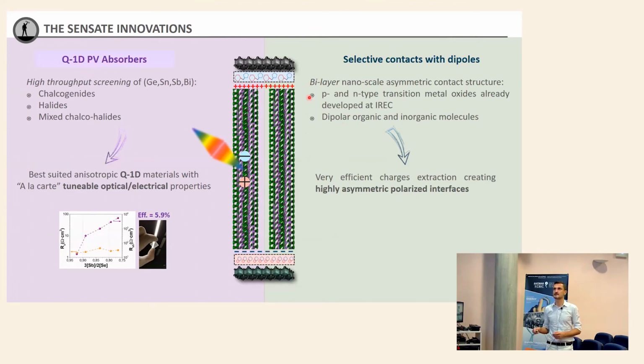absorbers. The characteristic of this material is that they have a very strong covalent bonding in one direction, in 2 directions, sorry, and then you form ribbons. And then these ribbons are bonded among them with van der Waals energy, so very soft energy. So you can use all this van der Waals space to dope the material, to put nanoparticles, to give the material special properties. For example, 1 year ago, more or less, we proved that putting selenium here, we can convert this material in this direction into almost an insulating material.